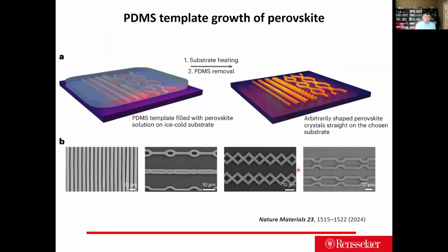I think after our work, Barbara also later candidly showed that this method can be extended from a hard nano-fabricated structure to a PDMS template. With the PDMS template, you can also grow various structures with spatial confinement. Those are really great structures and interesting things to study. For more detail, you can read Barbara's 2024 Nature paper. And I think the PDMS mask has more defect tolerance. This is also another big advance in the field.